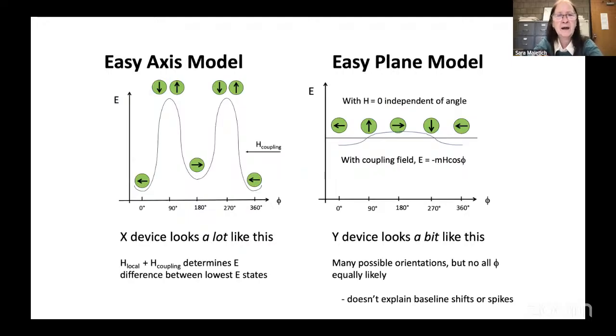What we could say, knowing what I explained earlier, is that the X devices act a lot like what you would expect for a monodomain particle with two relatively low energy configurations, the field due to the fixed layer favoring one slightly over the other, and an energy barrier in between them. This X device is going to spend most of its time in one of these two low energy states. To go in between, it has to go through a high energy state where the magnetic moment is perpendicular to the field, up or down, but it should not spend a lot of time there.